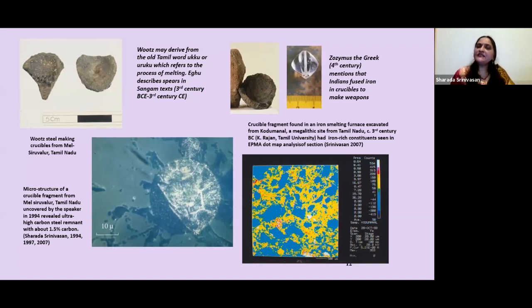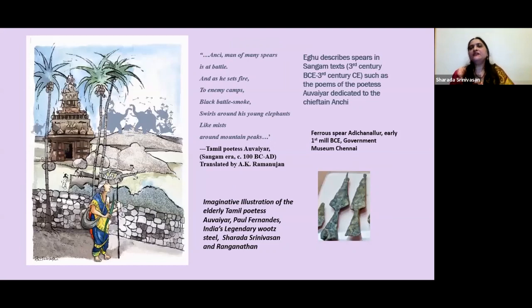I also studied some crucible fragments from an iron smelting furnace from Kodumanal, a megalithic site in Tamil Nadu, which also had iron-rich constituents related to ferrous processing. Now, the term wootz itself may derive from the Tamil word ukku or uruku, which refers to the process of melting. It's also interesting that Zosimus, the Greek in the 4th century, mentions that Indians fused iron in crucibles to make wootz. And this term ukku is also found in Tamil Sangam texts of the 3rd century BCE to 3rd century CE, in the poems of the remarkable bardic writer Avvaiyar, who dedicated several poems to the chieftain Anchi.